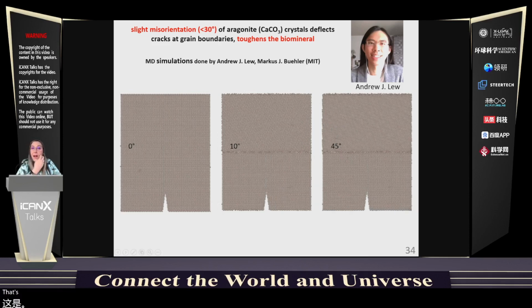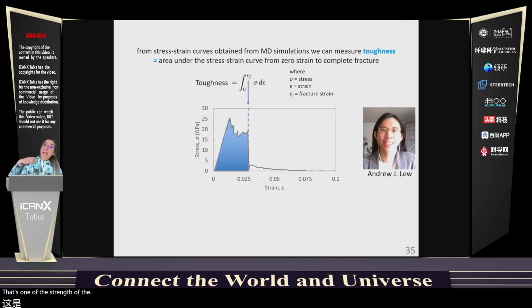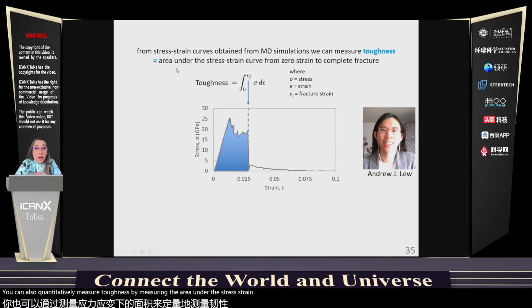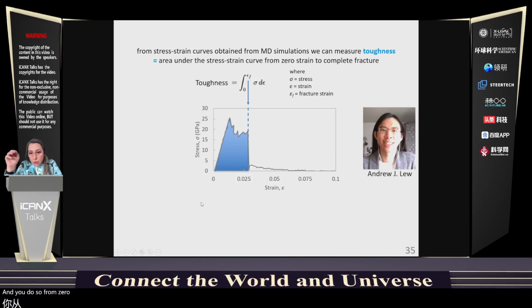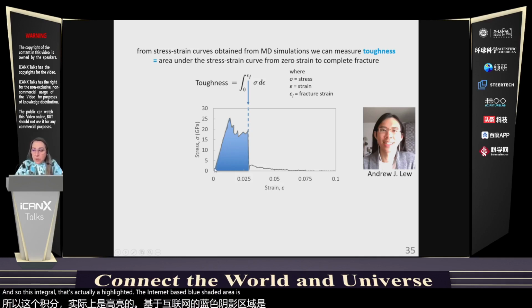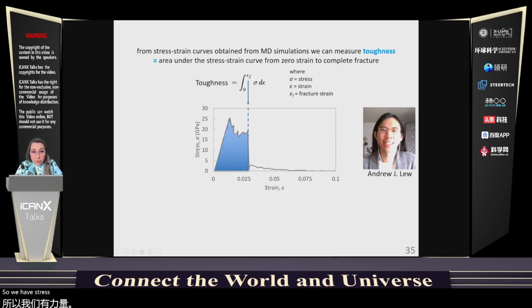That's one of the strengths of molecular dynamic simulations, is that besides looking at the pretty images we just saw in the movies, you can also quantitatively measure toughness by measuring the area under the stress-strain curve, and you do so from 0 to total fracture. And so this integral that's highlighted in this blue shaded area is measured quantitatively, and that represents the toughness. So we have stress, strain, and the integral between 0 and total fracture.